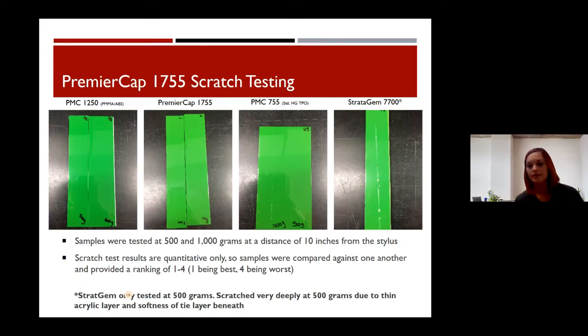So just some of the testing that we went through as we were working on the scratch and mar. Premier cap 1755, so it's the high gloss product. We have a small Gardner scratch. So when you think of scratch testing, it's a stylus, so it's a point contact. Think your fingernail. I'm going to scratch something with my fingernail. Same kind of thing, just a little more controlled. You can see off to the far left there is an acrylic. That's kind of the gold standard for scratch, as well as for mar. We tested the Premier Cap as well as standard high gloss TPO, and the Premier Cap performed nearly as good as the acrylic. So we were pretty happy with that.